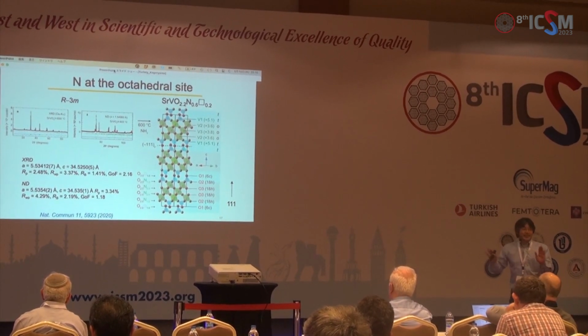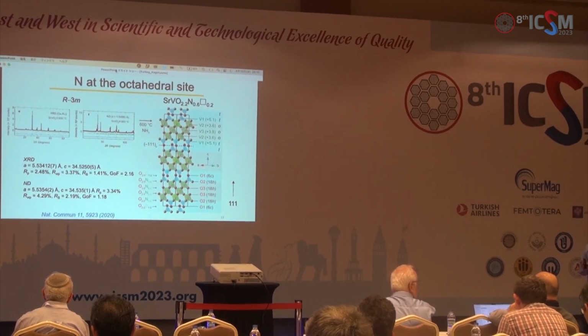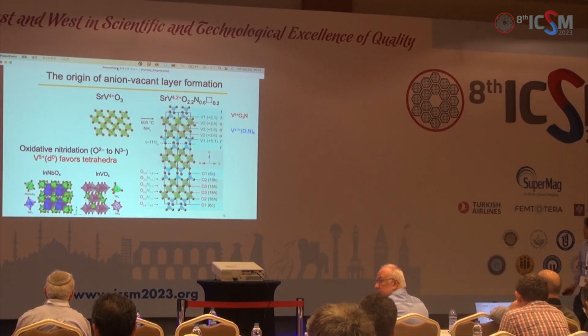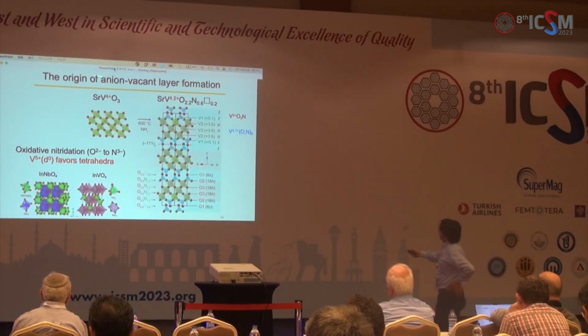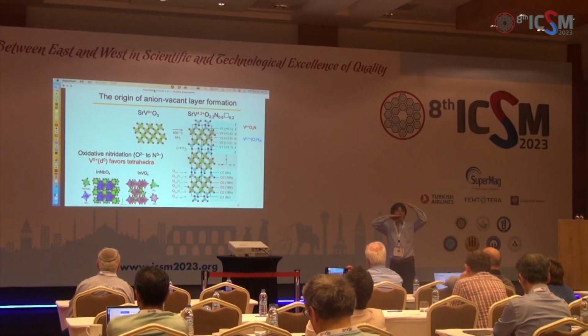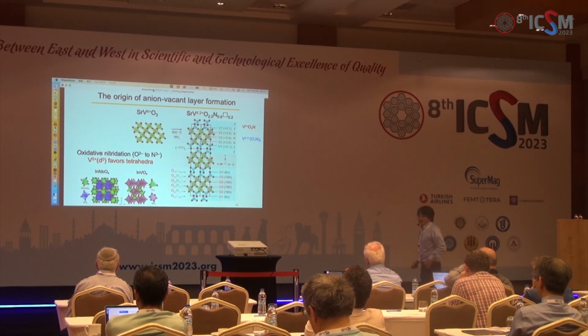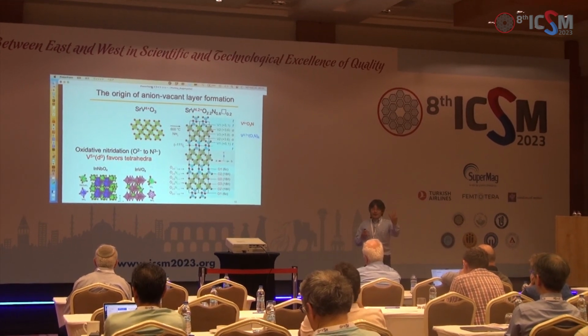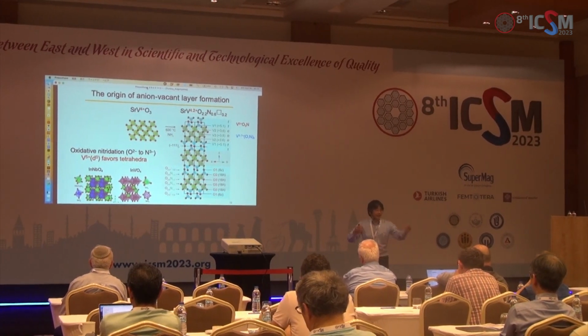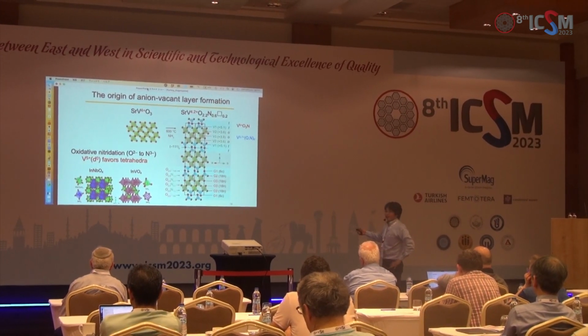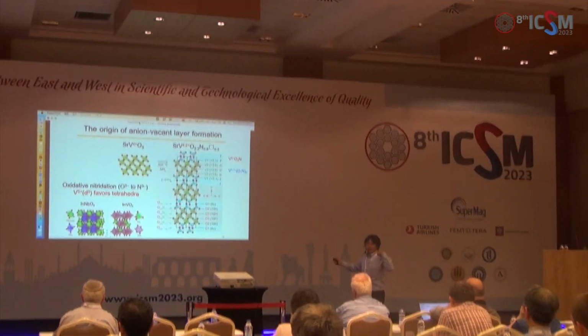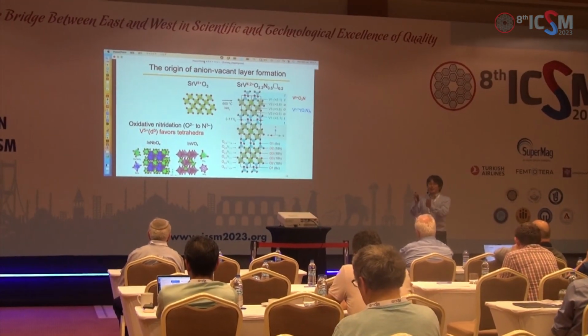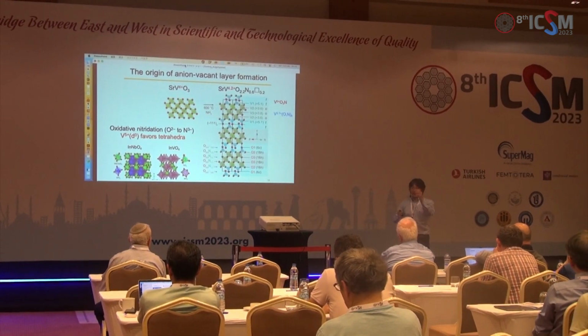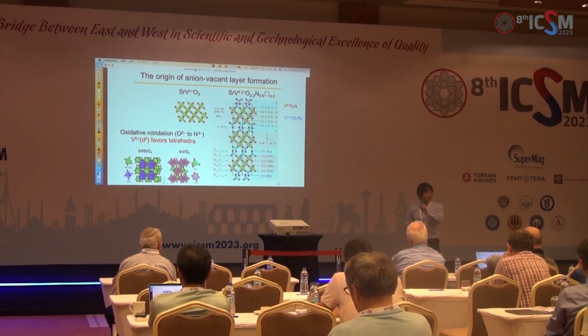So it's very complicated, but from a physics point of view, this material is very simple. Then maybe we should consider why this type of anion vacancy occurs. The reason is very simple. We found that our starting material is vanadium 4+. So exchange of an ion from oxygen to nitrogen is nothing but an oxidation reaction. The final material has the formal valence of 4.2+, which means that some of the vanadium takes the 5+ state.